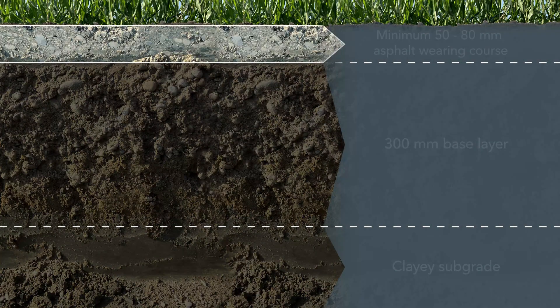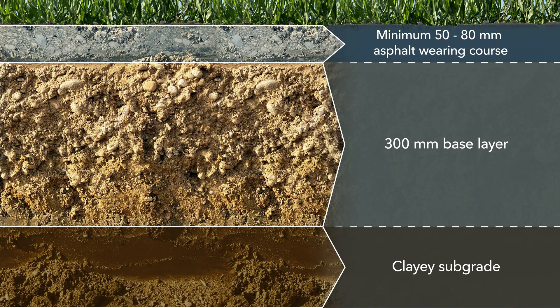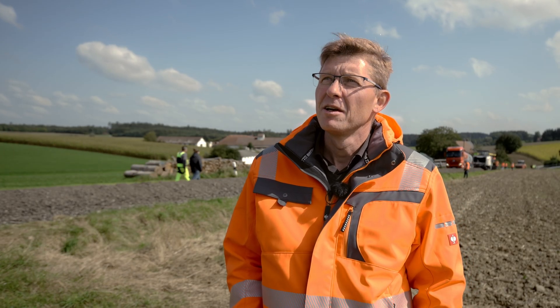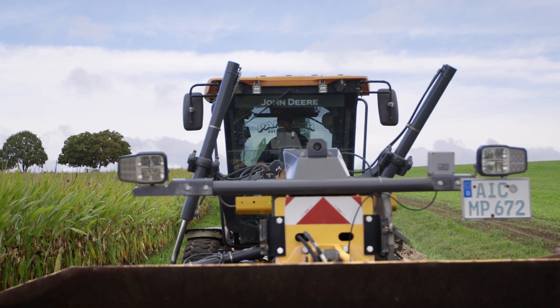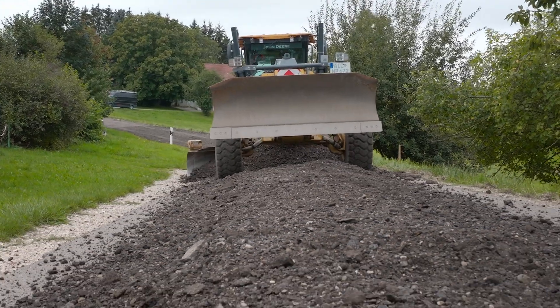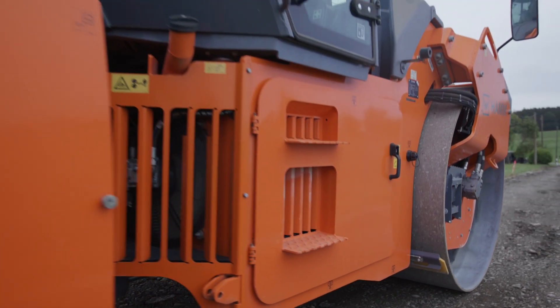We are realizing the project using the cold recycling process. Preliminary investigations indicate that there is insufficient recyclable material available — at least a 50mm to 80mm asphalt surface layer on a 300mm base layer on clayey subgrade. We have also topped up the roadway with milled material from another section of this construction site, so the structure to be recycled measures 150mm: at least 50mm existing asphalt surface layer plus 100mm pre-profiled and compacted milled material.